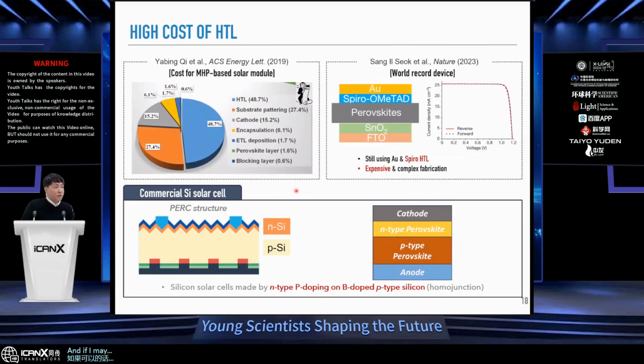And if I may give you the motivation for why doping in perovskites would be important, it is also because of its cost factor. So if we talk about the metal halide perovskite based solar cell module, a large portion of the cost of the module is actually composed by the hole transport layer, for which we use spiro-OMeTAD, like we use for OPVs as well, which is considered to be very expensive. And since that is the dominant cost factor, we come to a question, okay, why can't we eliminate it and use something similar to PERC structure that's already used for commercial silicon solar cells?